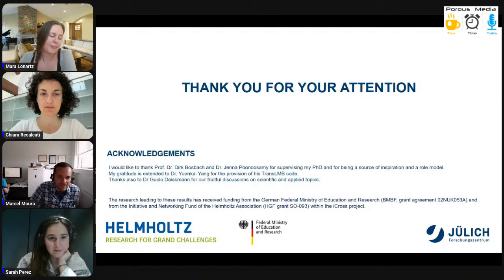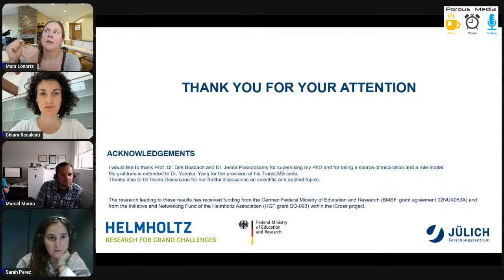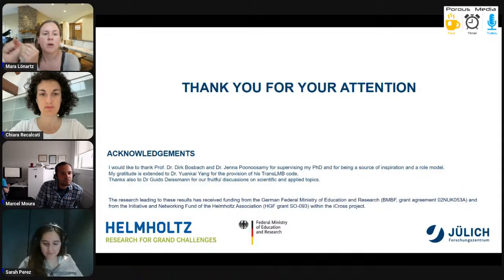I have one in the meantime. Did you also mention that you observed the dissolution of the solid, the PDMS? Does it attack the PDMS? I don't suggest so. There were limitations regarding the PDMS-glass chips because the PDMS is also altering at a specific time, and you can actually trace it, because when you do permanent Raman mapping, so if you measure the whole area by Raman, and the PDMS detaches from the glass, gas will come into your system, and gas is easy to measure.